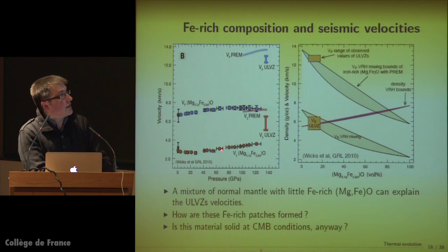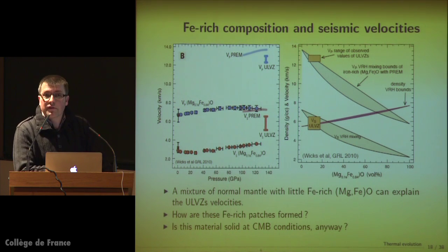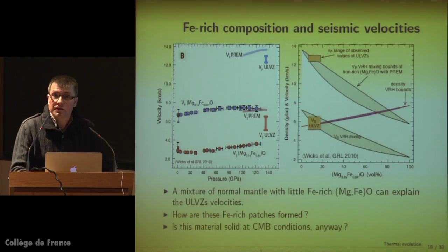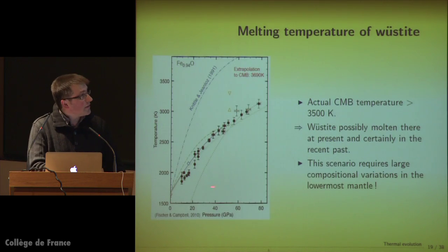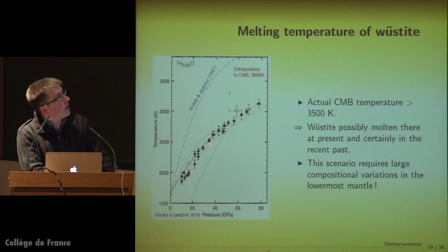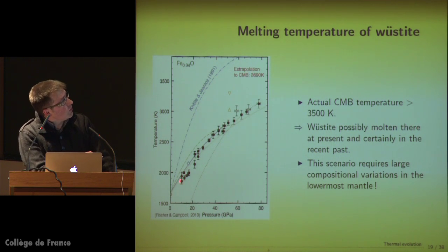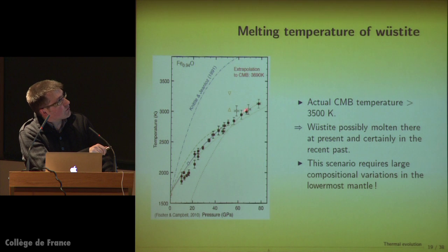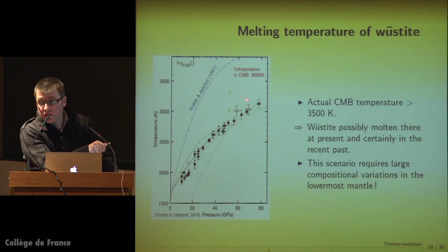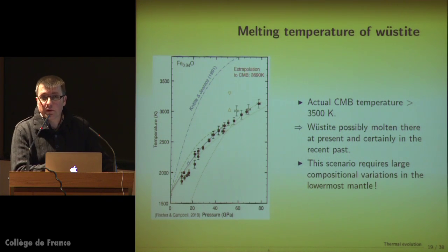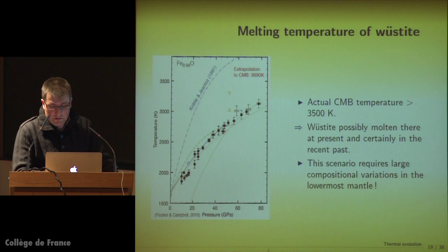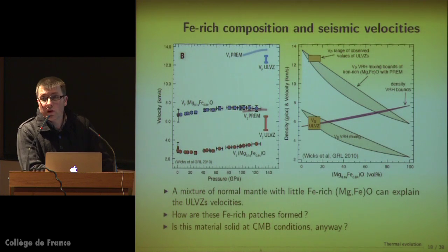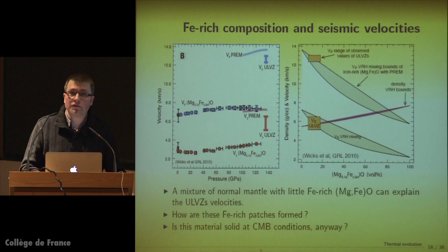And also the question is, would this kind of material still be solid at the conditions of the CMB? And it's not clear at all. For example, in this paper, the authors looked at the melting of wustite, and if you extrapolate this curve to the CMB conditions, you get a value that is typically the CMB temperature at the present time. So probably this kind of composition would actually be a liquid at the conditions of the CMB.